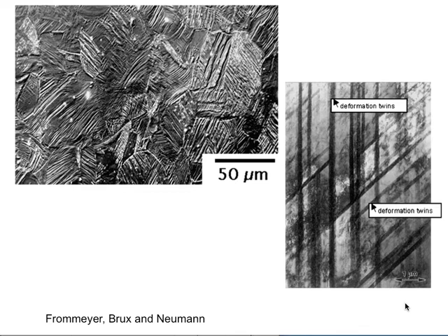So what do you think is the mechanism of work hardening? Yeah, this is like a dynamic Hall-Petch effect. In other words, as soon as you form a twin, you are dividing the austenite into two smaller grains, and this process continues as you deform. That is a transmission electron micrograph, and you can just about see that the scale here is 1 micrometer. So as a consequence of deformation, you've divided the austenite into incredibly small compartments. That contributes to work hardening capacity, and therefore we should expect a lot of elongation. There's no phase transformation here. Everyone happy with that?